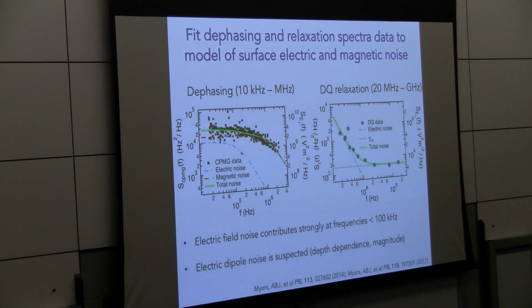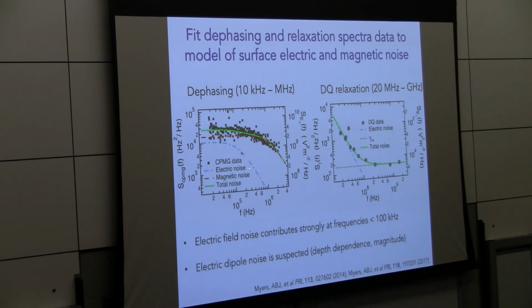And so we've done that recently, and here are the results, which show that we can map out both the electric and the magnetic noise components as a function of frequency. And I guess the upshot here is we find that electric field noise, surprisingly, contributes strongly at frequencies less than 100 kilohertz, and given the dependence of the noise on the depth of the NV, we suspect that that's a dipole noise. So these are really efforts to try to understand on a more microscopic scale what is the origin of noise at these surfaces and how can we mitigate that.